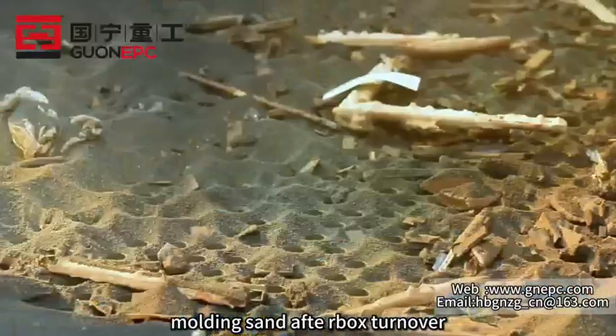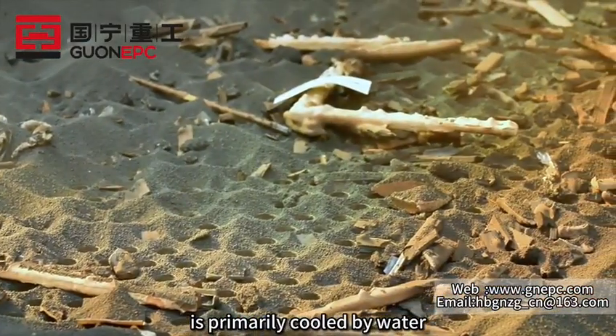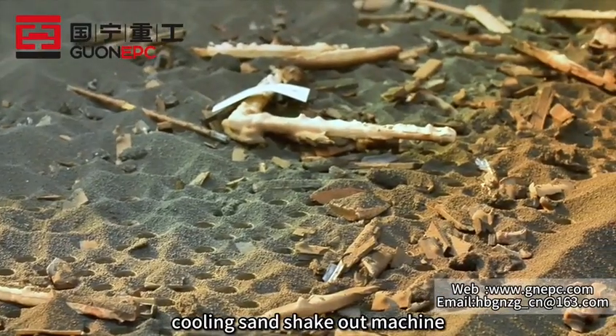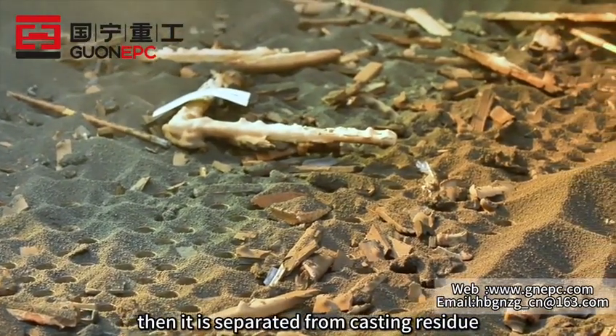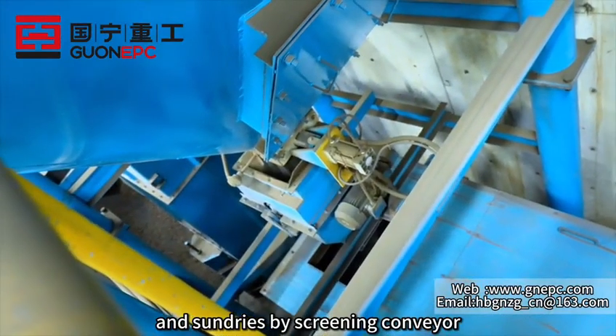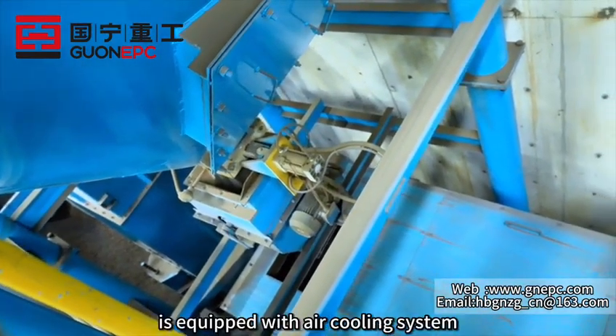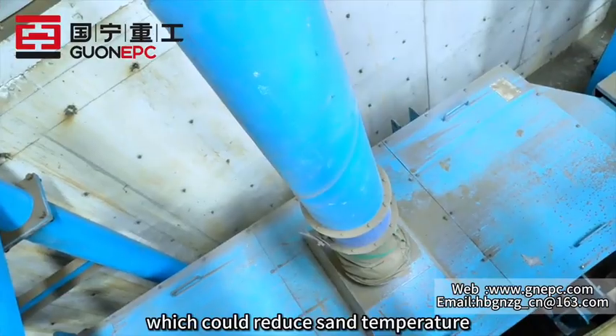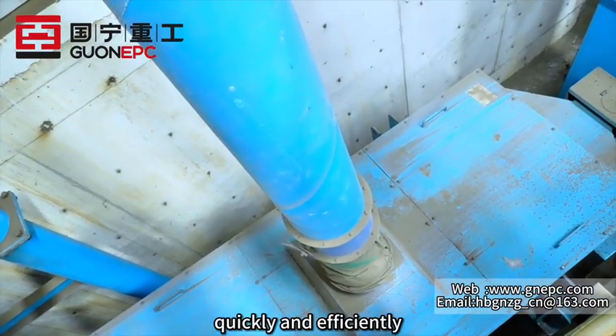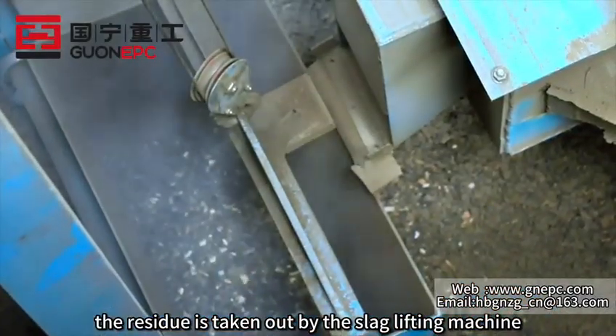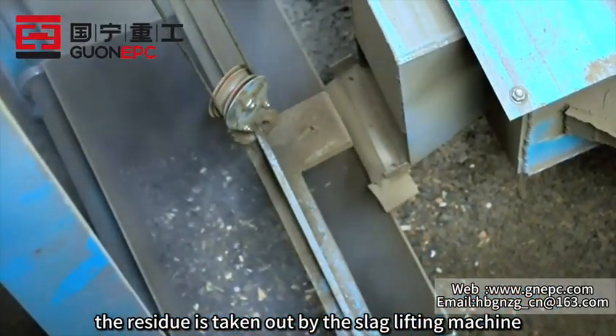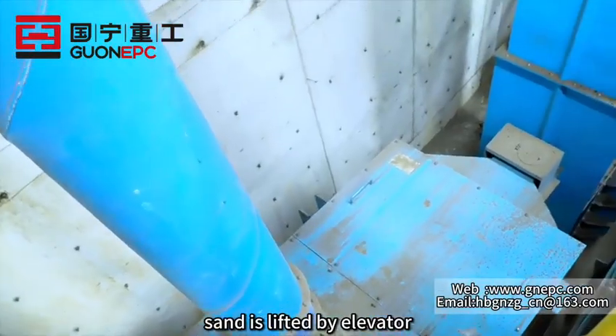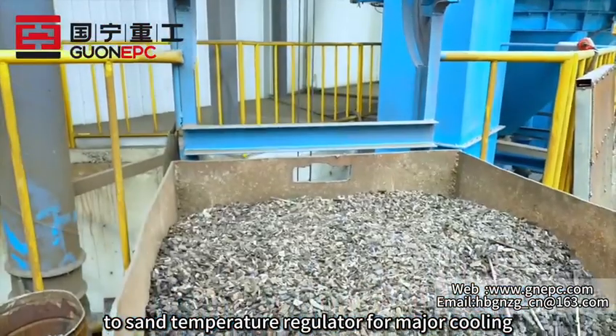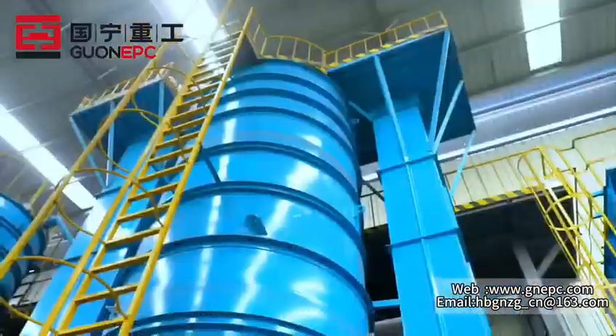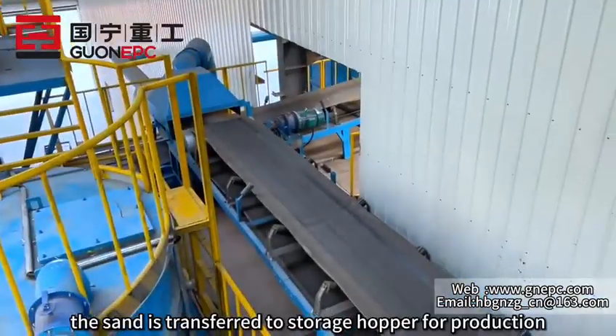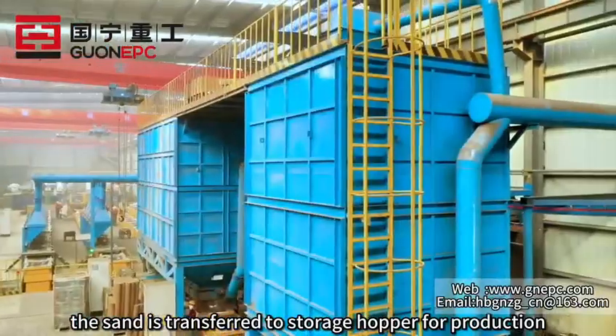Molding sand after box turnover is primarily cooled by a water cooling sand shakeout machine. Then it is separated from casting residue and sundries by a screening conveyor. The screening conveyor is equipped with an air cooling system, which can reduce sand temperature quickly and efficiently. The residue is taken out by the slag lifting machine, while the molding sand is lifted by an elevator to the sand temperature regulator for major cooling. After all these processes, the sand is transferred to the storage hopper for production.